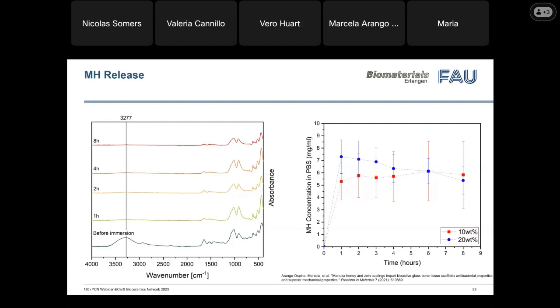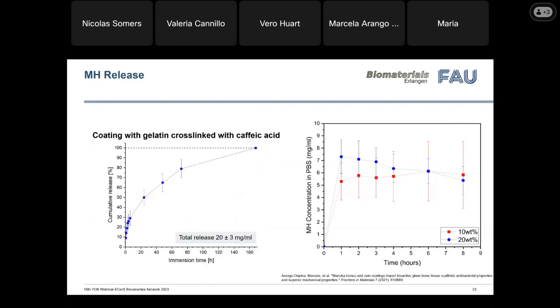So we started trying to optimize this system to see if we could get a more sustained release. For this, we started working on another coating. Here we use gelatin and we cross-linked gelatin with caffeic acid. So we can observe better results. Here is the release during a period of 1 week.